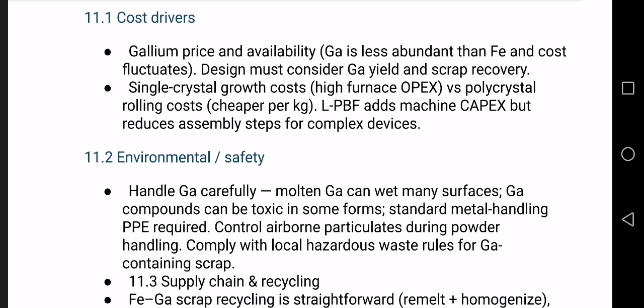Polycrystalline rolling route: casting, rolling, annealing, much cheaper per kilogram. Uses standard steel processing infrastructure. Advantages are good mechanical properties, scalable, cost effective. That is why most industrial FeGa components are polycrystalline.